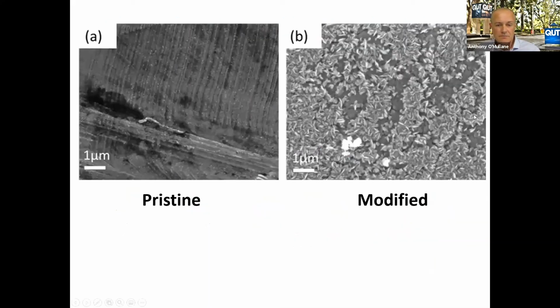So if we look at some SEM images, pristine steel, as you can imagine, it's relatively rough as it's polished. We didn't want to smooth it down too much, so we took it as received. And then when we did our electrochemical treatment, we can see that we're getting these flake-like structures, which are highly indicative of layered double hydroxide type materials.